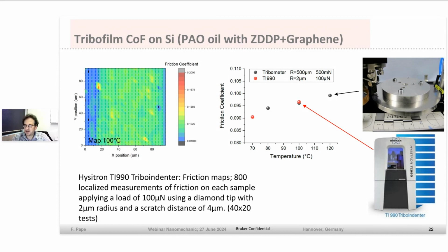And we compared that to the measurements done at the micro pin on disk tester, which we could also put in an oven up to 70 degrees or 100 degrees. And we can see that these curves fit quite well to the measurements done with the nano scratch tests. So here we can really see some local coefficient of friction of the ZDDP-based tribofilm. And I hope we can proceed with this work in the future too.